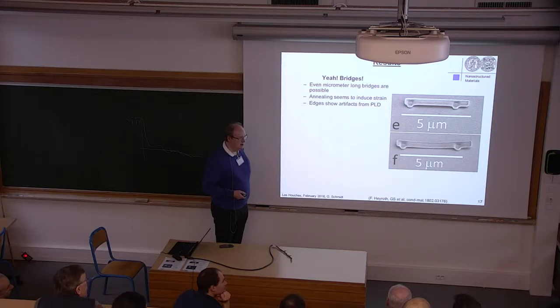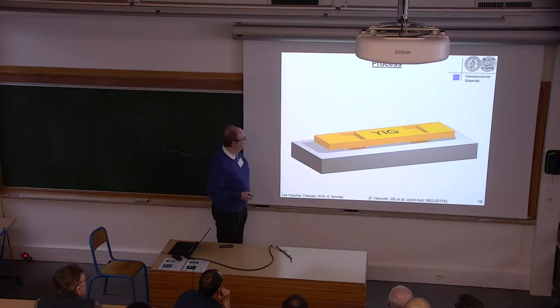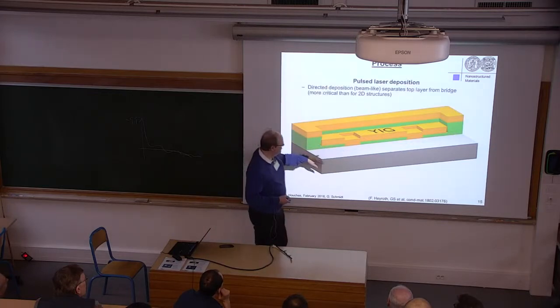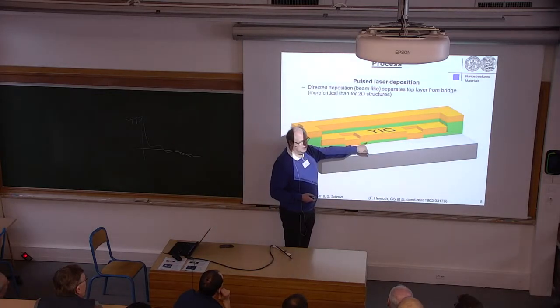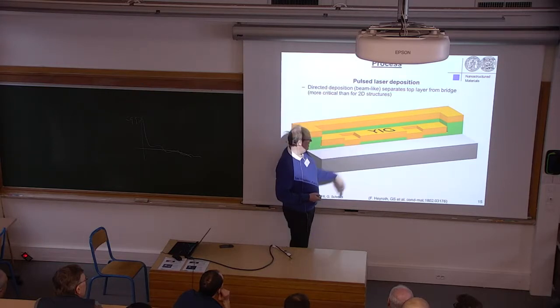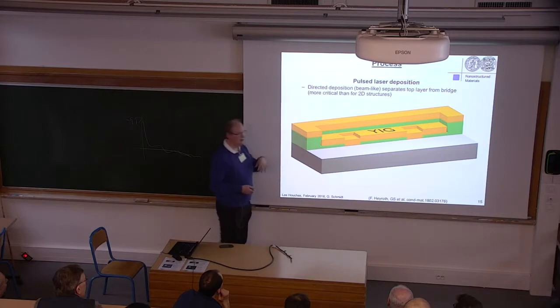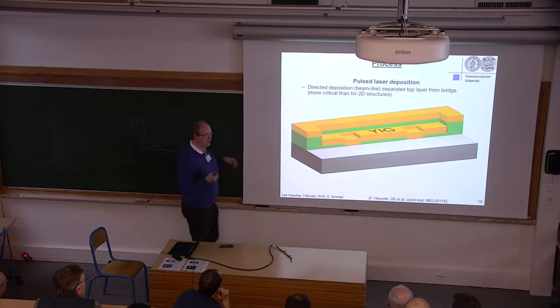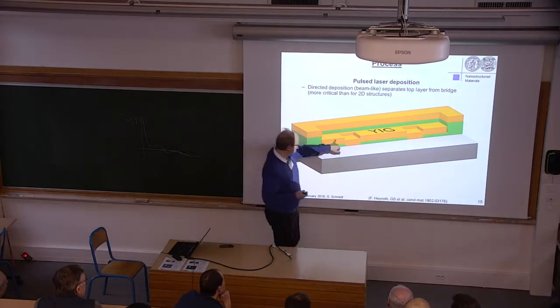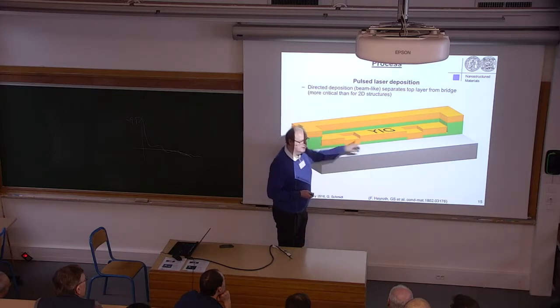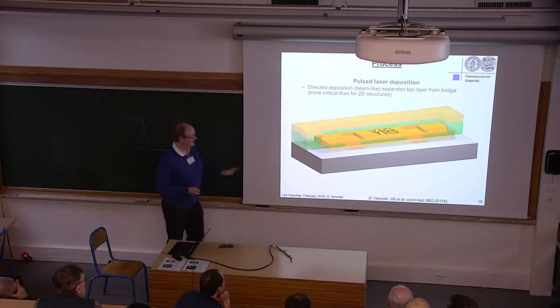Sorry, and the size of the height, is it about the thickness of a film? How much you lift it up? Yeah, wait a moment, I can go back there. So this here can be, we have done between 50 and 200 nanometers already. And it just depends on how much you grow. Actually, you can use pretty thin films because it's not as ideal as this one. You get some bending over here. You will see it in the next picture.